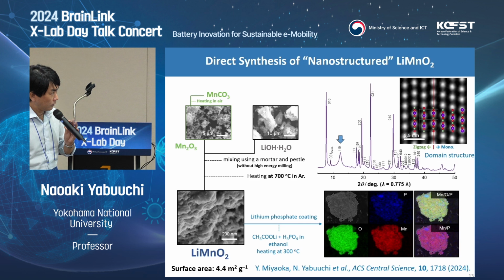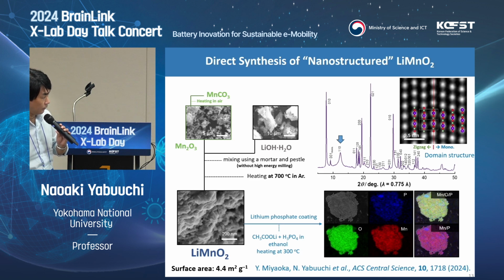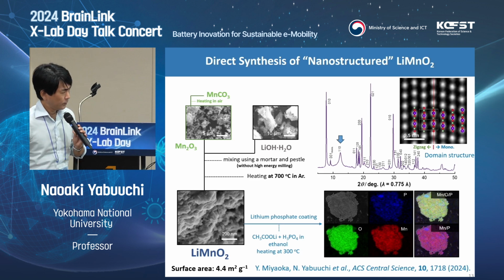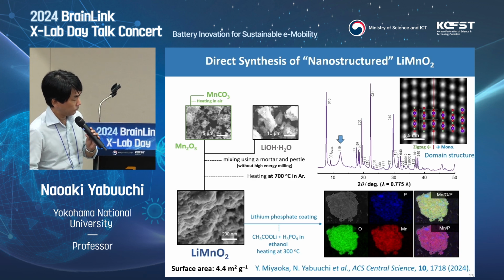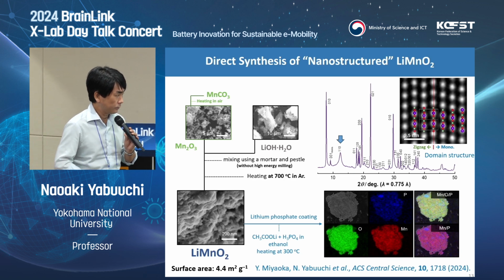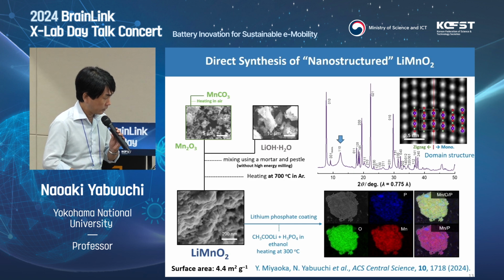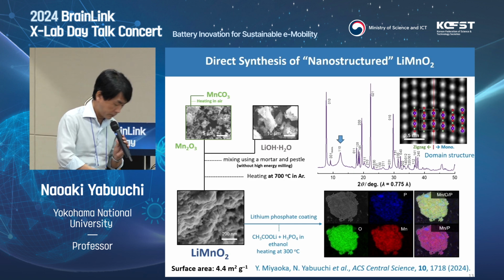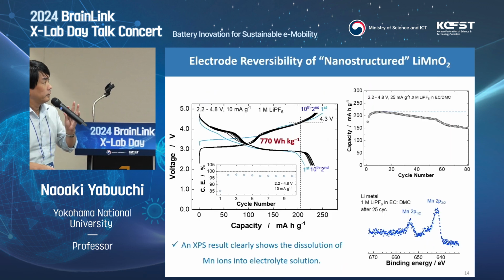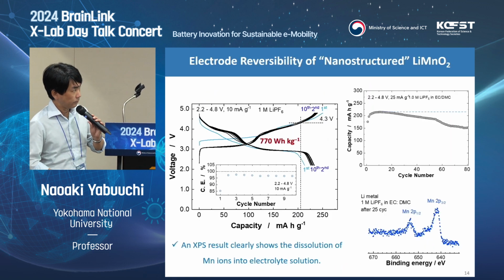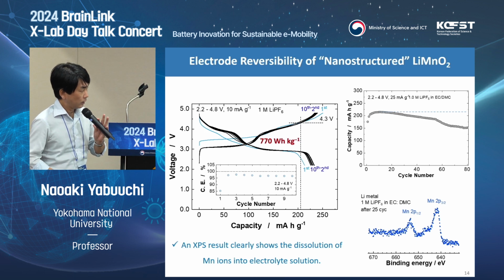So by optimizing our synthesis conditions, we have a low crystallinity, domain structured lithium manganese O2. And also we still have a solubility problem for manganese ions. So the surface was coated by lithium phosphate. This is also a very simple strategy. So this sample, nanostructured lithium manganese O2, can deliver large reversible capacity from initial cycles.